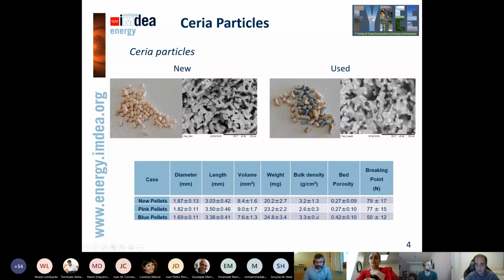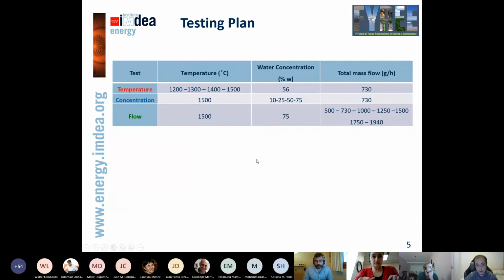And here in the bulk density, pink particles, which are those that are more or less the same as when they got into the reactor at first, present a relatively smaller bulk density, but the main difference is here in the breaking point. We used a dynamometer to measure it, where the blue pellets seem much more fragile than both the new and the pink ones. Nevertheless, you can see those differences in the particles, we saw no negative impact on the reduction rates.